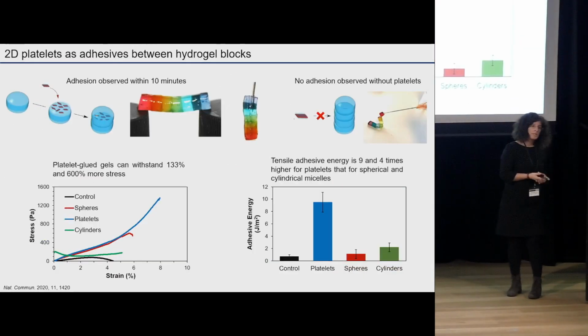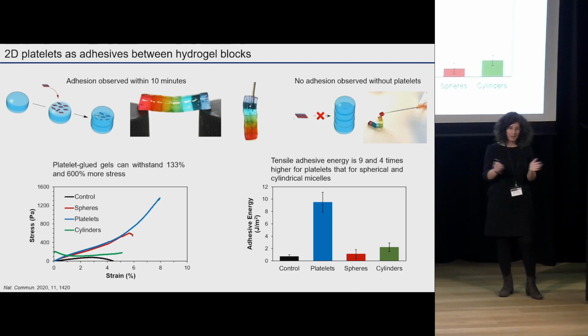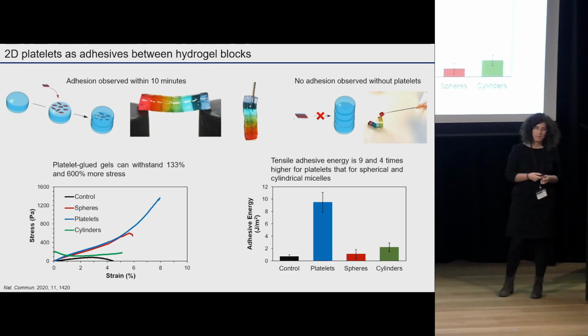So what we did was to see if any of these nanoparticles had adhesive properties, and we repeated the experiment that I showed before in the Nature paper. We cut alginate hydrogels in different blocks, and then we put the nanoparticle in one block and tried to adhere the other one. And what you're seeing here is actually a rainbow gel made from different blocks of hydrogel, glued together and suspended between 2 vials.